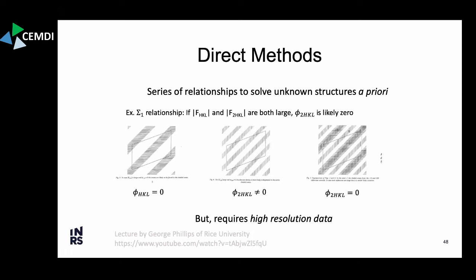And this argument comes from trying to look in real space. If you have a strong reflection, this would actually be the diagonal, so this would be the 110. If you have a strong reflection, then you're going to have a lot of electron density at the nodes in the 110 reflection. And then if you look at the 220, it's unlikely to have this sort of phase mismatch. So this would be the case where the phase is non-zero, because you can see that you don't have the high electron density going through the center of your unit cell. And it's more likely that if both structure factors from 220 and 110 are big, that you have these overlapping of electron density. And that's the essence of direct methods, using these reasonings to develop a library of arguments to limit down the possibilities of the phases.